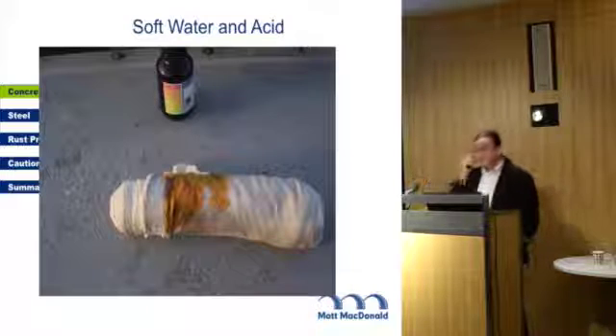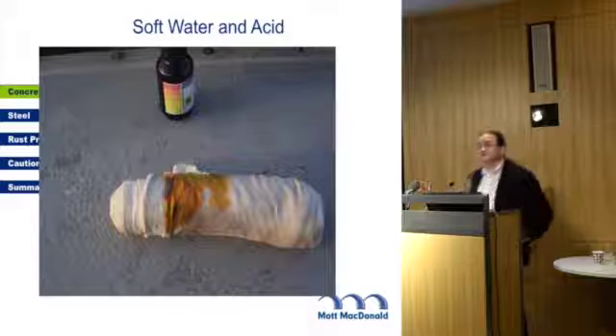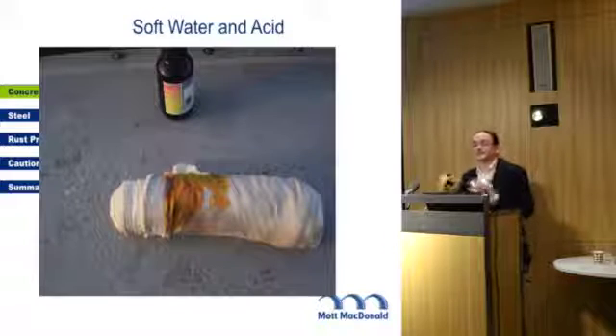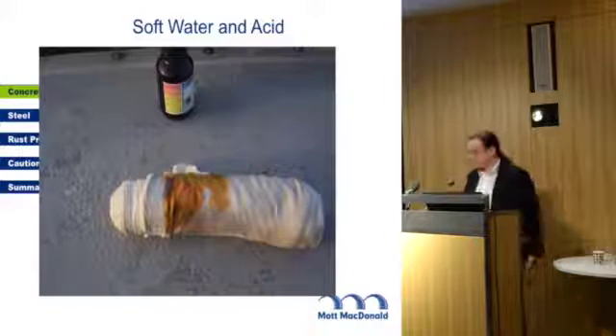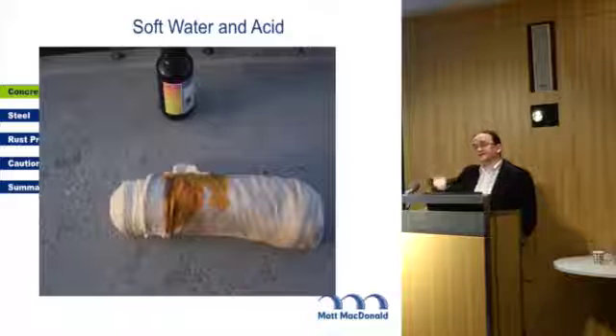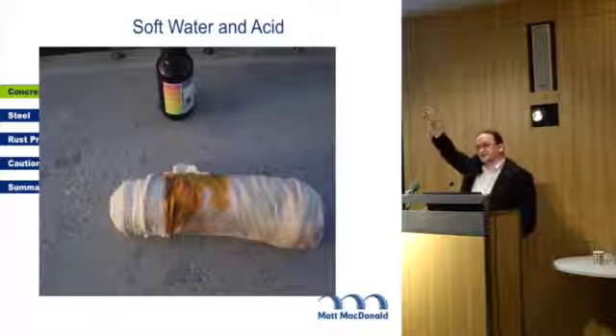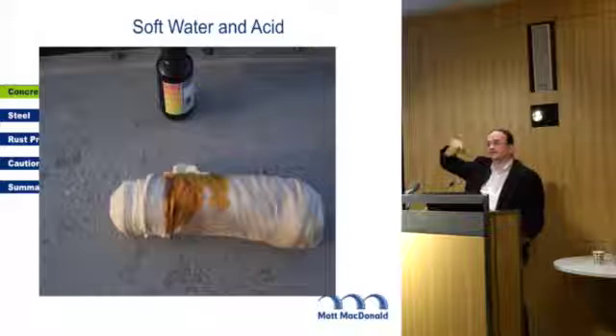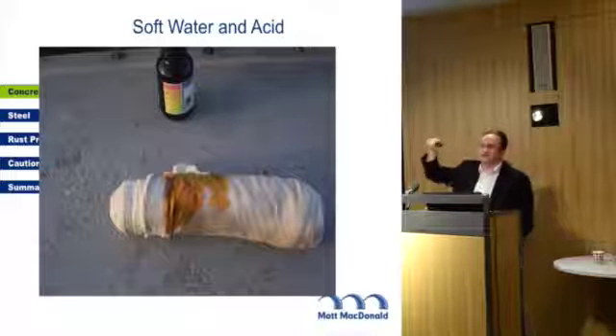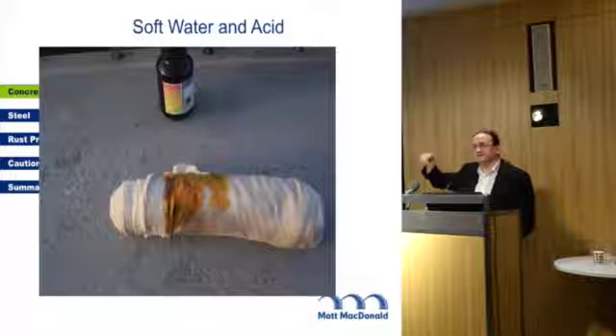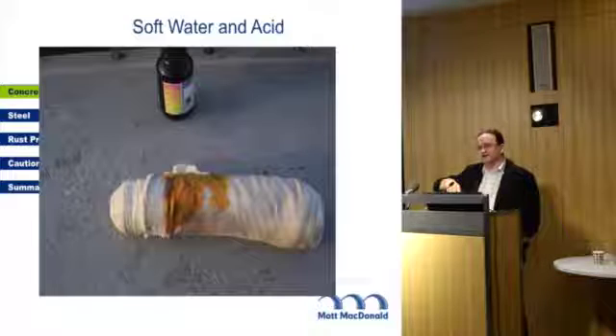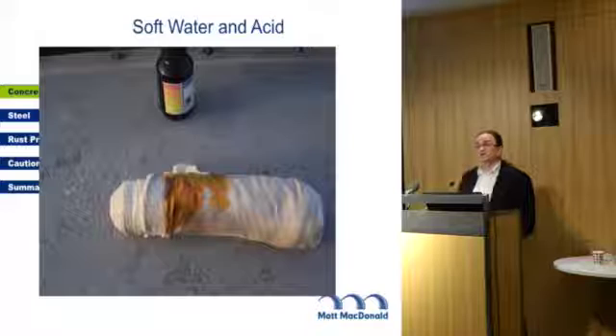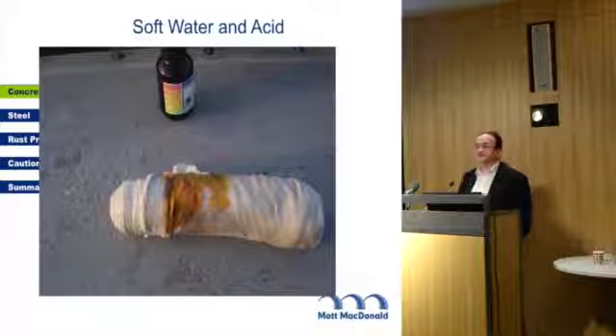That's a GRP lid. What that does, the smell in sewage is hydrogen sulfide. That happens when you digest sewage. If you put a lid on the tank, the hydrogen sulfide collects on the underside of the lid. There you get oxygen-reducing, sulfur-oxidizing bacteria that react with this hydrogen sulfide and turn it into sulfuric acid of about pH 1. Net result, you lose about 10 millimetres of concrete a year.